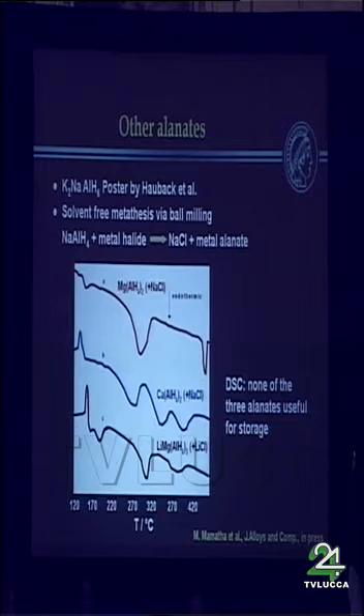There are other alanates. There is a poster on the potassium-sodium AlH6 outside. The group of Dymova has reported calcium alanate 3 years ago. I show you here 3 DSC traces for the ball-milled alanates: magnesium alanate, calcium alanate, lithium magnesium alanate. So it's again this metathesis reaction: sodium alanate plus the metal halide gives sodium chloride plus the metal alanate. You have the sodium chloride in there, but you can use the mixture to evaluate the thermodynamics.